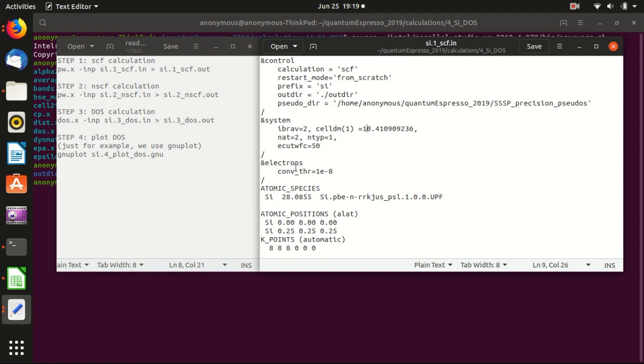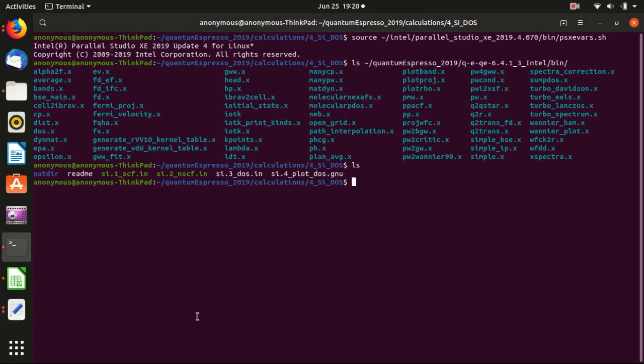I also improved the convergence threshold for the electrons, lowering it to 1×10⁻⁸, so that the calculation is more accurate. The other settings are not changed. I also increased the k-points to 8×8×8, because this is just a single point calculation — not a relaxation that would invoke many SCF cycles. So you can set k-points to be larger; the more k-points you have, the more precise your calculation will be. In this case I use 8×8×8.